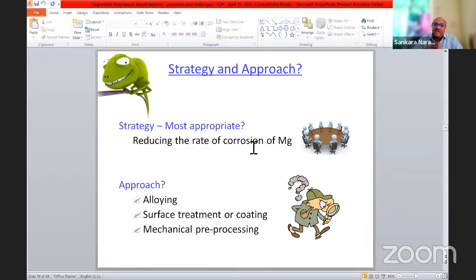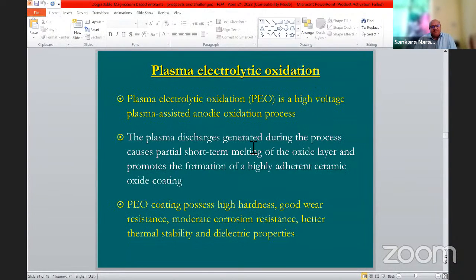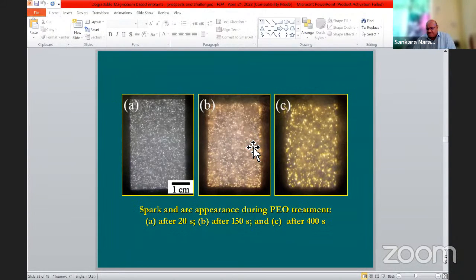So that alloying element should not be toxic. Magnesium is not toxic, but the alloying element should also be not toxic. In that case, you have only a limited number of alloying elements, manganese, zinc, etc. So the best choice is surface treatment or coating. So we have developed some surface modifications and coatings. One of them is plasma electrolytic oxidation. Basically, it's a high voltage anodic oxidation process. It forms a porous oxide layer.